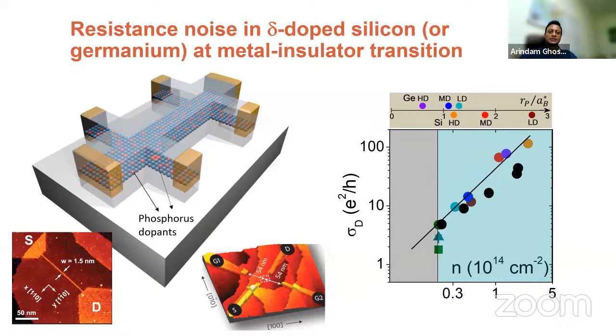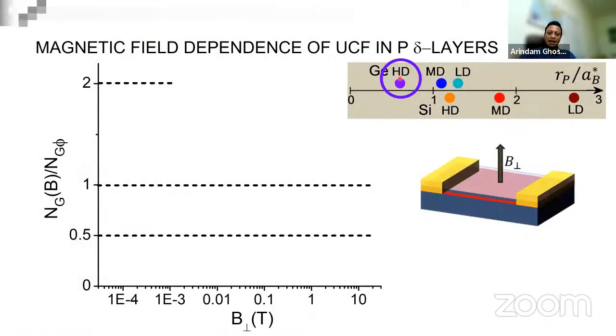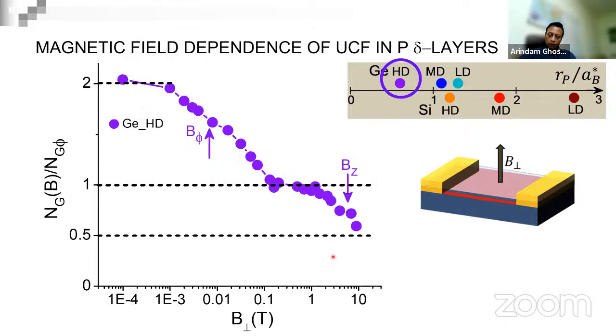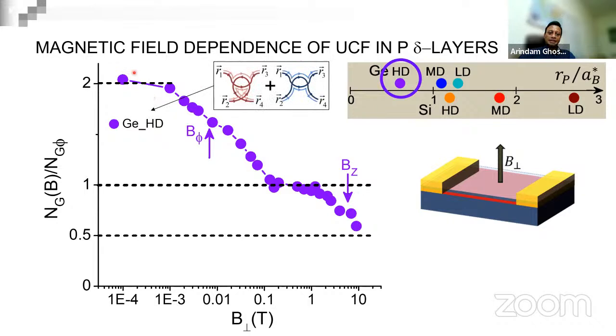Remember, silicon, phosphorus, and there's nothing else, they are all non-magnetic system, right? Then we realized that this is where we should measure the noise. If I measure noise at sufficiently high density, where the interaction is low, the noise reduces by twice. As you increase the magnetic field, noise decreases exactly by a factor of 2, as I showed you, removal of Cooperons. And then there is another factor of 2 reduction because of the Zeeman splitting. In this sample, when interaction magnitude is very small, it gives you both contributions from Cooperons and diffusons. Hence the noise is a factor of 2 higher.